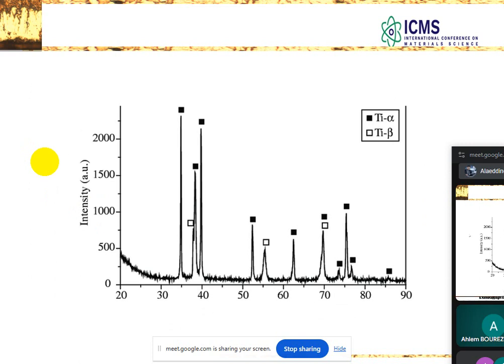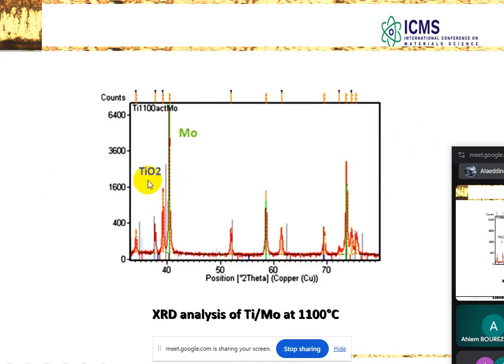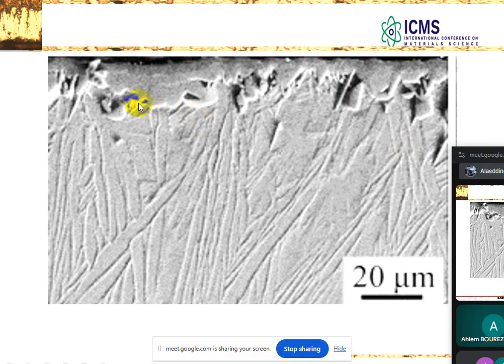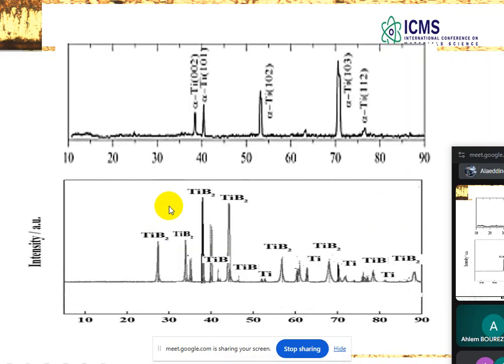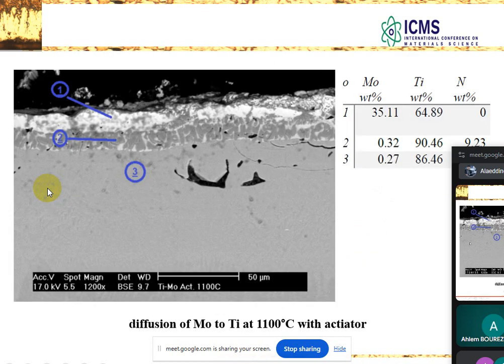So this is the boride layers that we have. For non-treated titanium alloy, as you know, we have only alpha and beta phases. After the treatment, we found in the titanium alloy composition molybdenum and boron. This is the boride layers, dental like this, formed on the surface of the titanium alloy. And after that, we have TiB2 and titanium alloy, alpha titanium. So we have boride from this treatment.